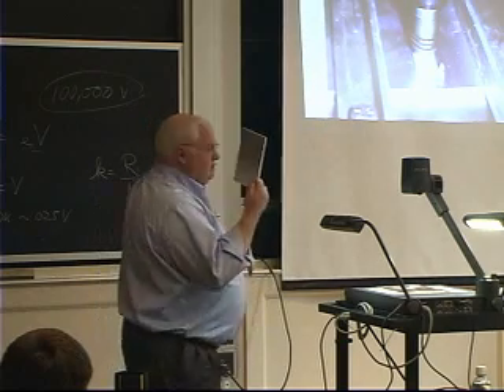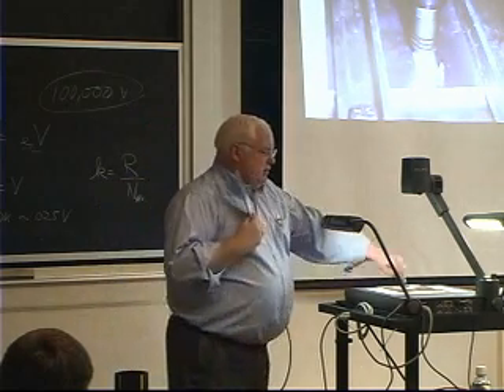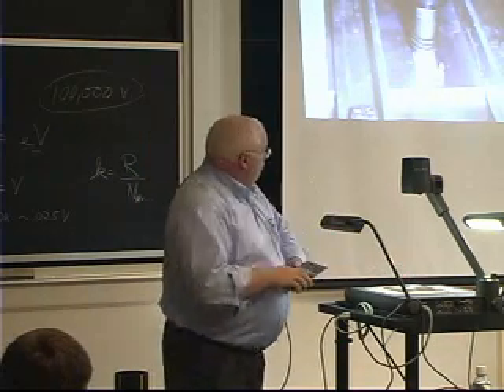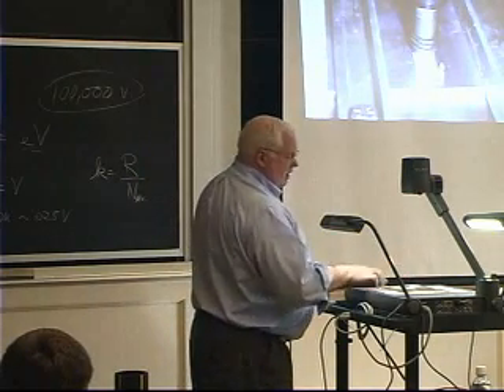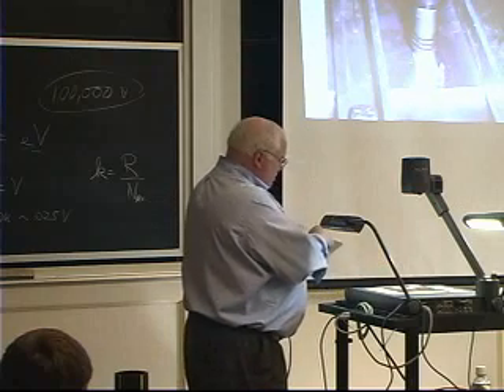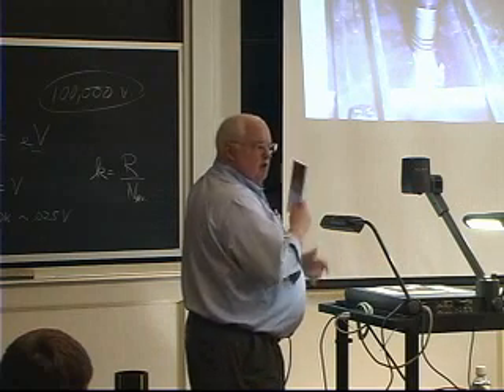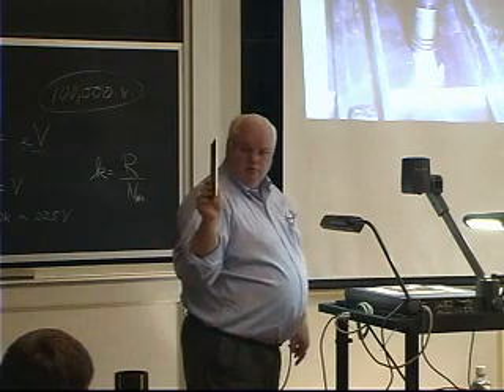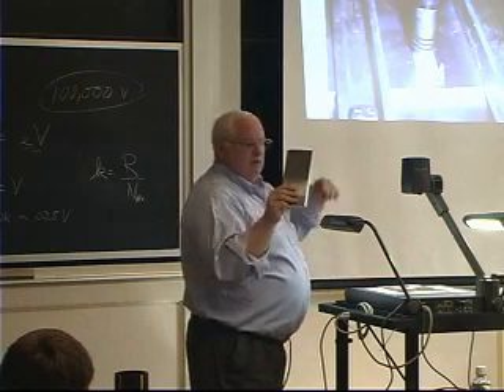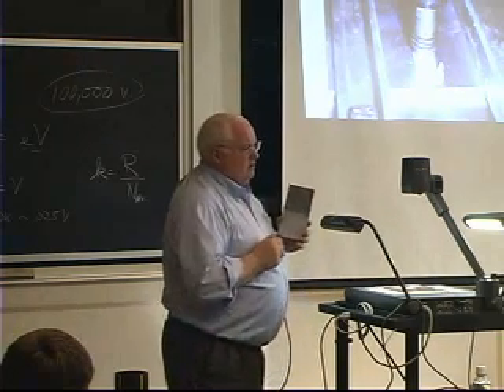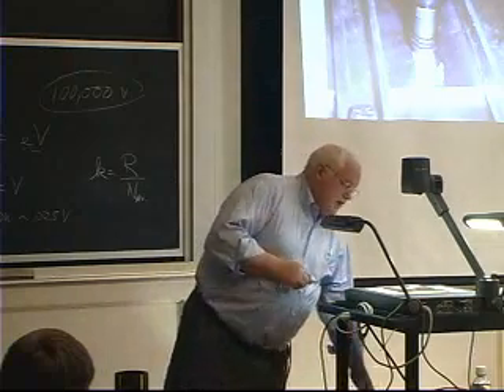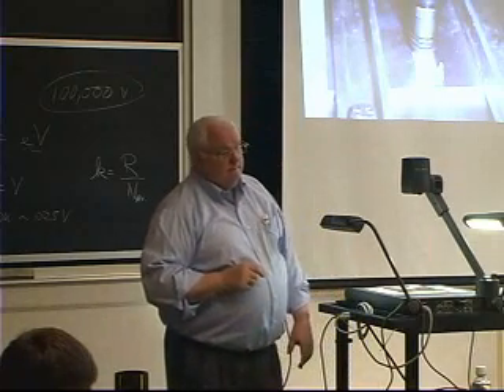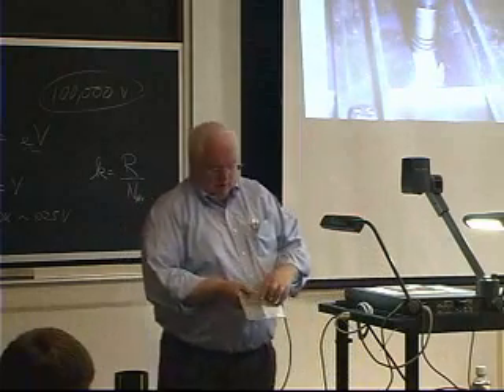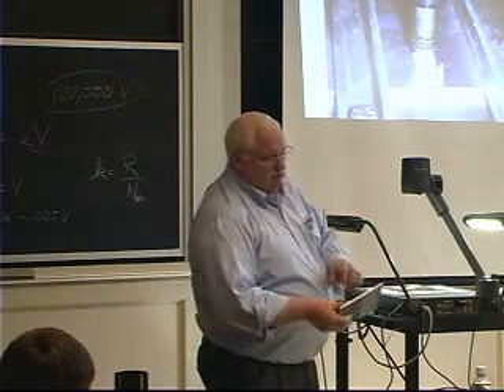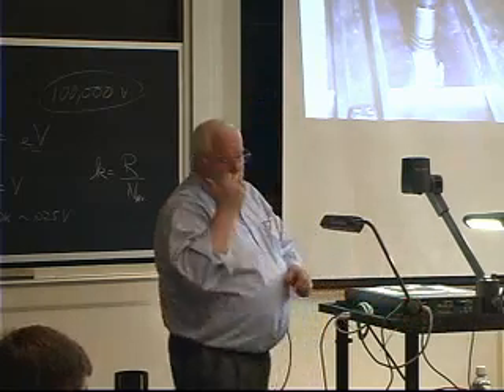This is a NASA friction stir weld. They basically take a mandrel and fixture the plate very, very well. They come in and spin the mandrel around and just move it along the plate and make a weld with very little distortion. If you compare that to an arc weld, those plates would be bent 15 degrees for a typical fusion arc weld. It's a solid state process. Does it only weld the surface? No, it goes all the way through. The mandrel actually pushes down beneath the surface. They have done up to half an inch thick. Boeing is doing friction stir welding right now.